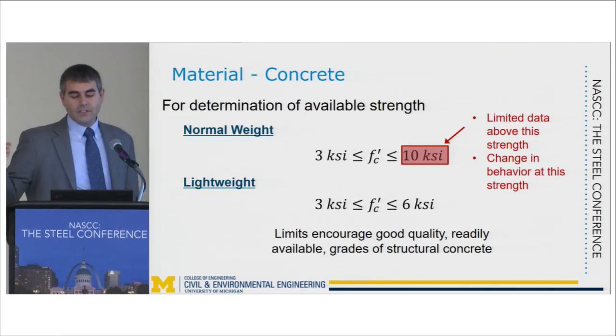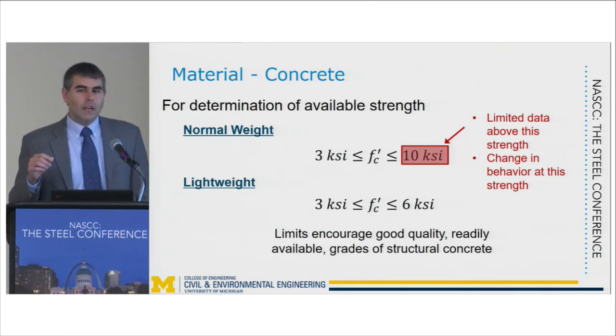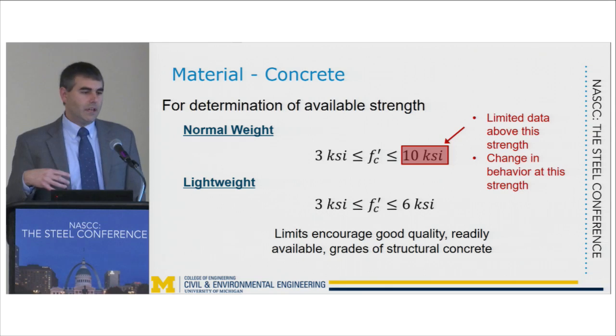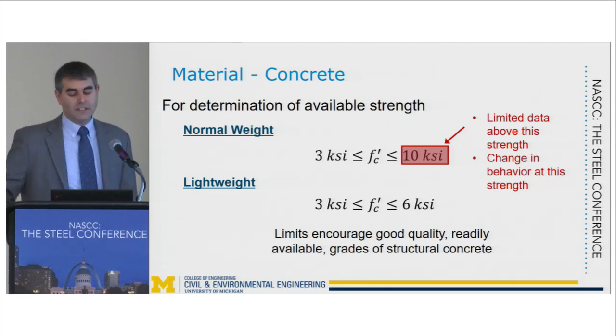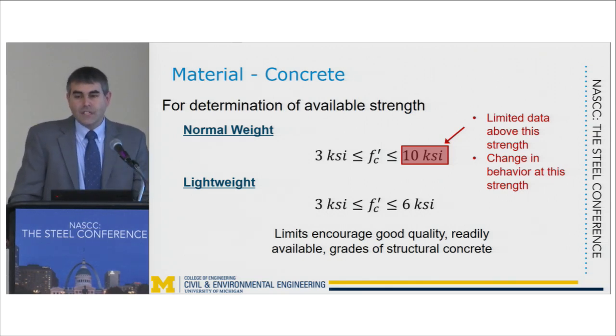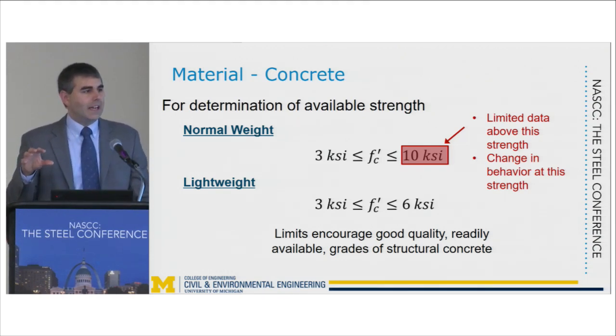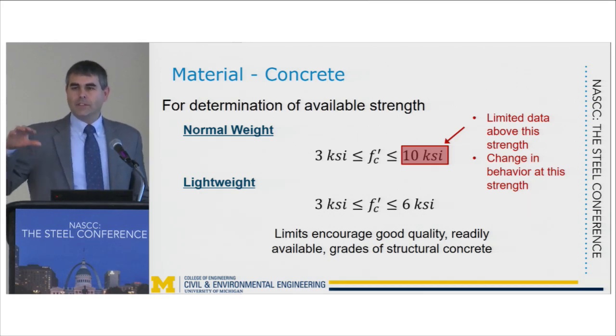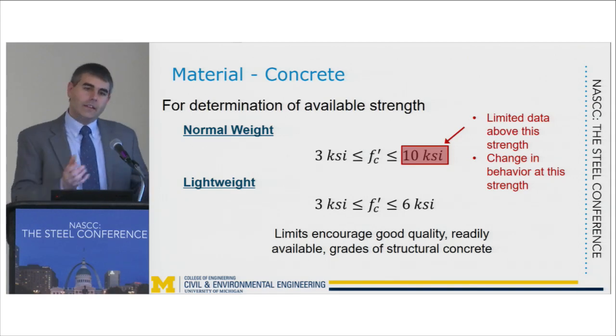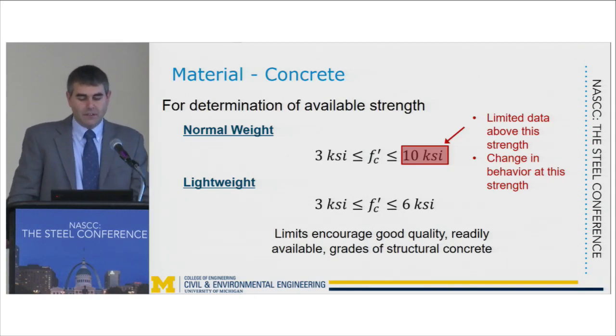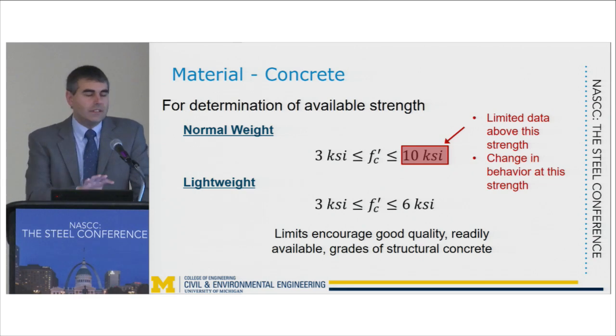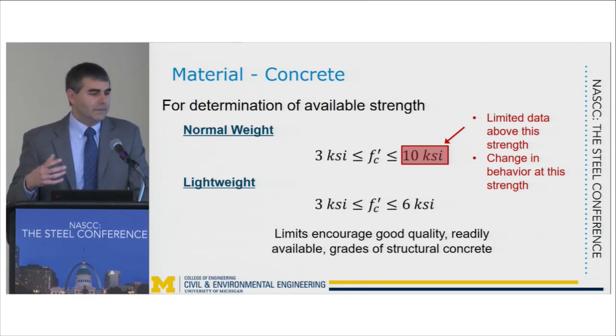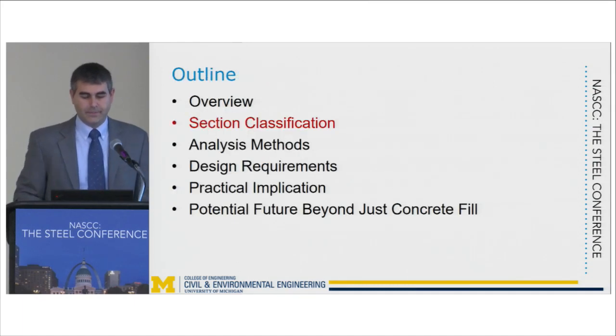Now, that 10 KSI limit is mainly there because there's not a lot of research that's been done with concrete-filled hollow structural sections with higher strength materials. And also, some of the research that has been done here in the U.S. has shown that 10 KSI strength is kind of a boundary where you start to see a different behavior occurring after that point. And because of that, the chapter I equations may not necessarily apply. Also, in general, these limits for the concrete tend to encourage good quality, readily available grades of structural concrete.